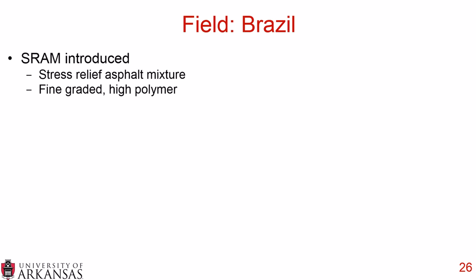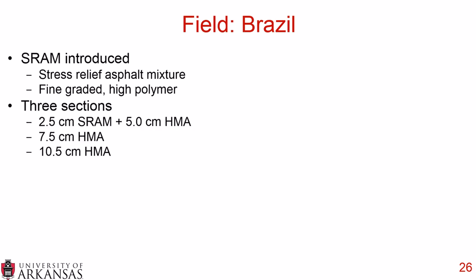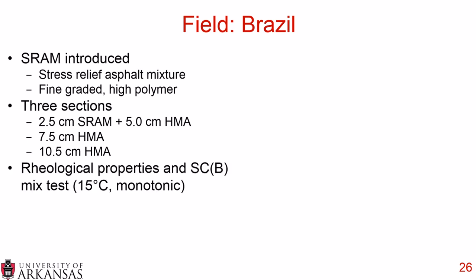And finally, moving to Brazil, they did a very nice field experiment where they looked at SRAM, which stands for a stress relief asphalt mixture, and this is a fine graded high polymer mixture. And they placed 3 sections in the field. They placed 2.5 centimeters of SRAM plus 5 centimeters of HMA, and they compared that to 7.5 centimeters of HMA, so the same thickness, but then also a slightly increased thickness of 10.5 centimeters.